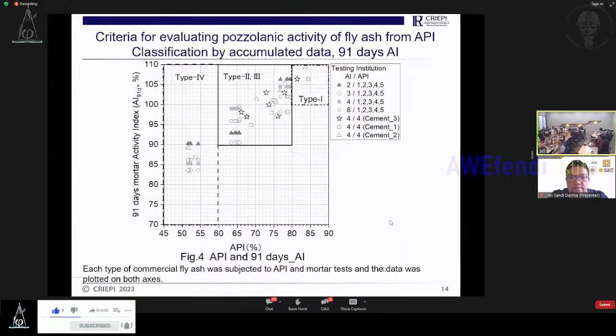There's also a linear relation between those values, and the results show like the plot. The API and the lower limitation of the activity index are shown like this. For the mortar activity index, for type 1 the lower limitation was 100%, for type 2 and type 3 the lower limitation is 90%, and type 4 shows the lower limitation as 70%.